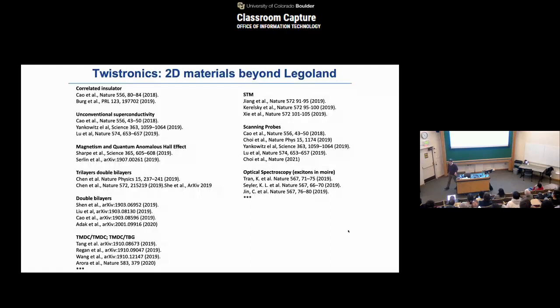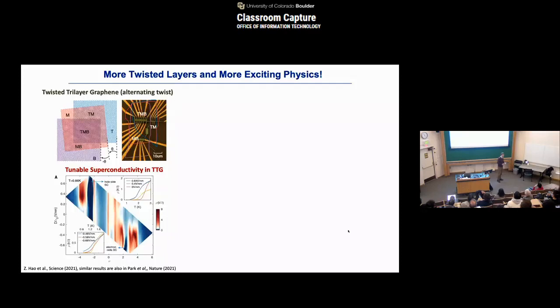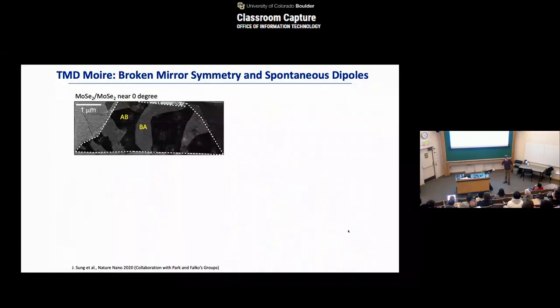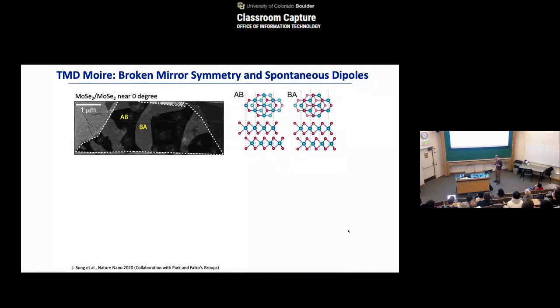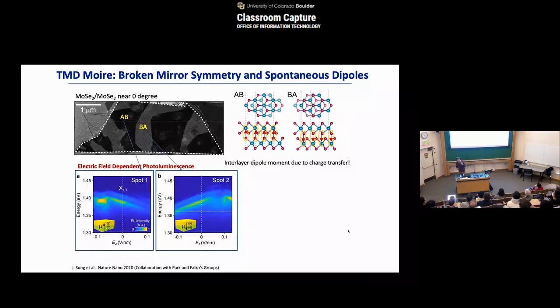Ever since those studies, the field actually exploded. Many groups were drawn into the field trying to understand all these weird phenomena that appear, including superconductivity, magnetism, Chern insulators, even fractional Chern insulators. And not only just 2 layers, the study went to 3 layers, 4 layers, 5 layers, not only single layer graphene but bilayer graphene, and transition metal dichalcogenides. This kind of study explored various different types of systems by just using twisting, which provides a somewhat different engineering capability to turn these materials into something rather different from what you start from with the single layer. And that's quite exciting.